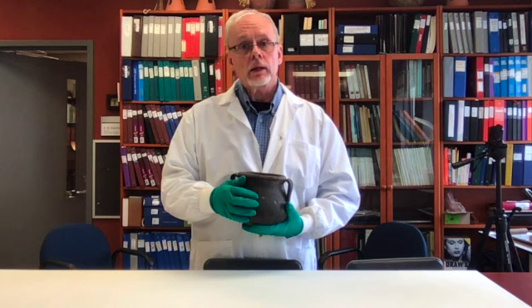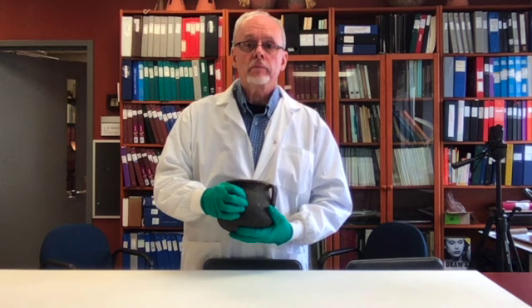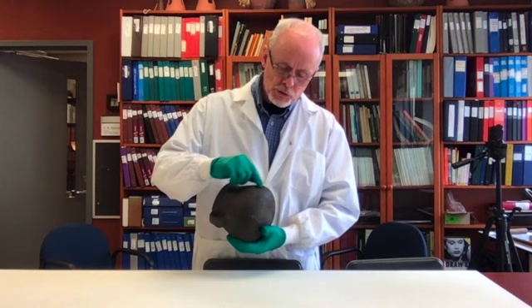For example, this ethnographic cooking pot has little chips on the bottom that come from resting on stones in the fire. It also has spalling on it in various places which probably was a result of heat expansion, so when this was heated up little inclusions in the paste of the pot probably kind of blew out of the side of the pot, so that probably is suggestive of having been used on a fire. There's also a certain amount of soot in some places on the exterior of the pot.